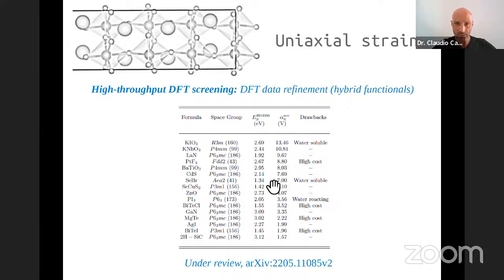The same happens for some other similar materials like this one here, or this other one here, which anyway were not known in this context of catalysis. However, we find out some nice results. For instance, we found out this potassium niobate, which is on second, but effectively it's on the first position, because it's not water soluble. It's pretty much ideal from a cost, from a band gap, from a band tunability point of view. So it's the one that goes on top of our list, and in fact, we just found that some very recent experimental reports in the literature have found that this material is a good piezo photocatalytic material. So a good thing that our search just found this material, but it's not totally new, so to say.